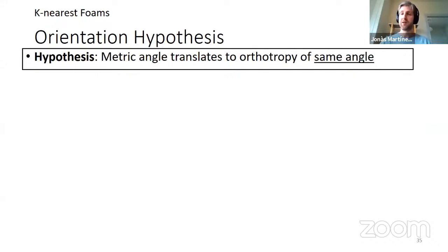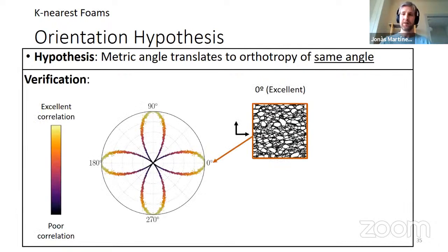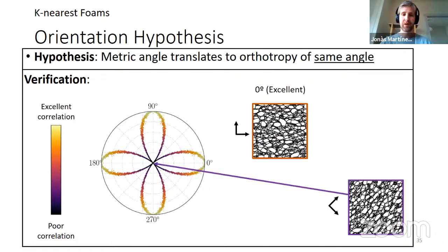Regarding orthotropy, we wanted to verify that these stretched k-nearest graphs are actually an orthotropic material. We posed the hypothesis that the metric angle translates to the same angle of orthotropy, and through numerical homogenization we have verified this. Here you have a plot where the points that are closer to the outer boundary indicate close agreement with orthotropy, and the others indicate the contrary. As you can see, there is a close alignment with the orthotropic axis.